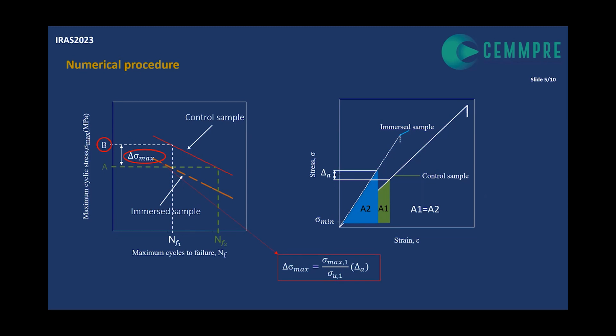So now what we have, very concisely, is a methodology to calculate the fatigue life of an immersed sample through the control sample SN curve. What we need is always the SN curve of the control sample and the static response, which can be simulated with a numerical model.